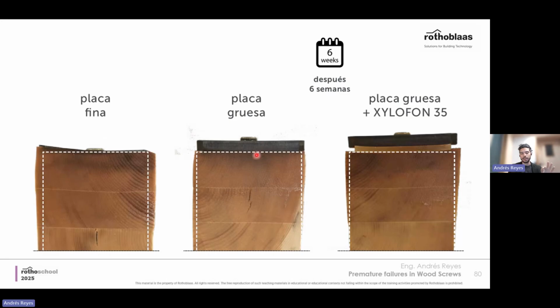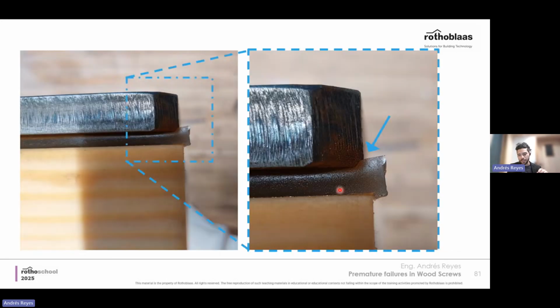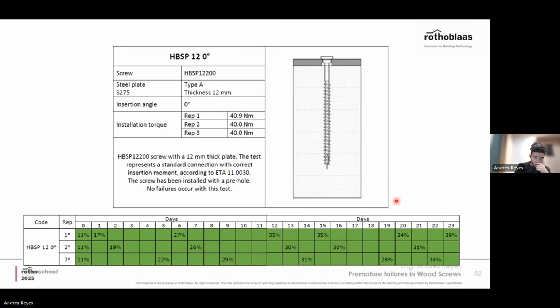In these cases of thick metal plates, you see that the metal plate didn't move. So in this case, a lot of the deformation, more than in the thin metal plate, was absorbed by the connection. And finally, damping solutions, you will see here the effect. It helps us perceive as well the effect of the wood swelling and how present it is. So the results were that with correct installation, wood swelling didn't break any case.